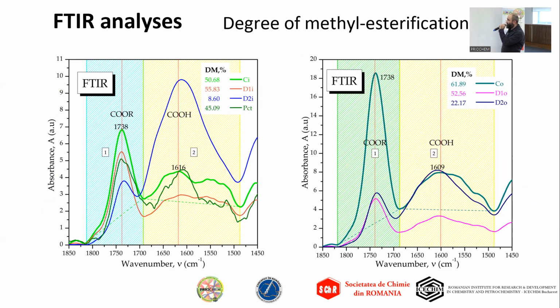The two bands for esterified pectin and free carboxyl groups can be used to evaluate the degree of methyl esterification by a ratio between the areas, and we can quantify, or semi-quantify in this case, the decrease of the degree of methyl esterification from 50 to 8 for the second dosage. Also, for the inner leaves and for the outer leaves, from 61 to 22.